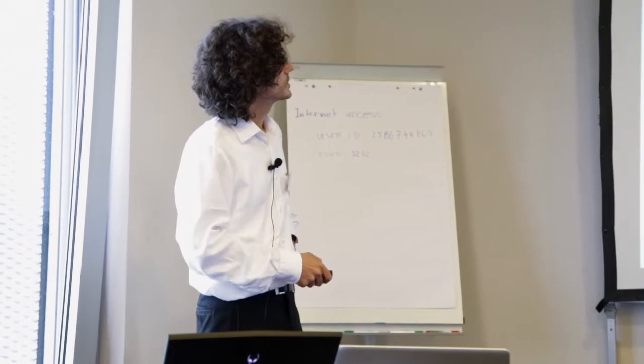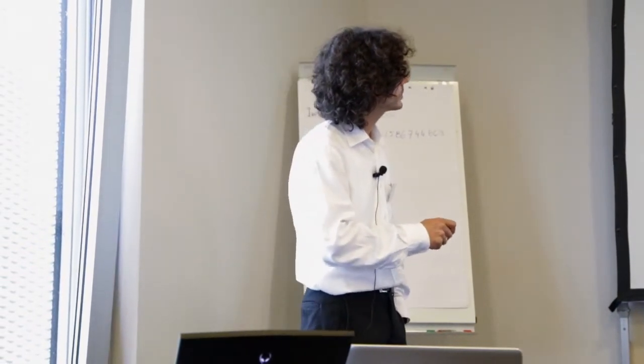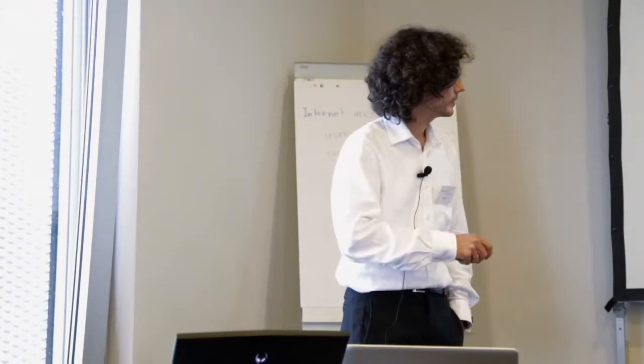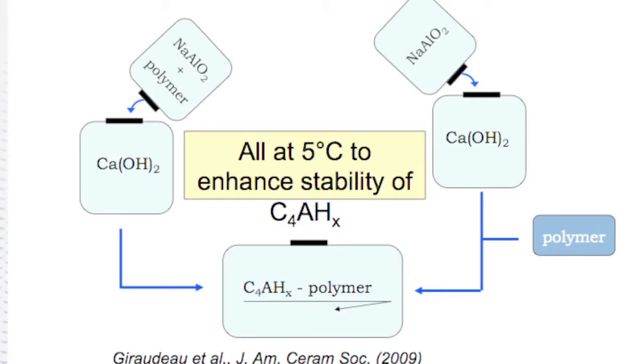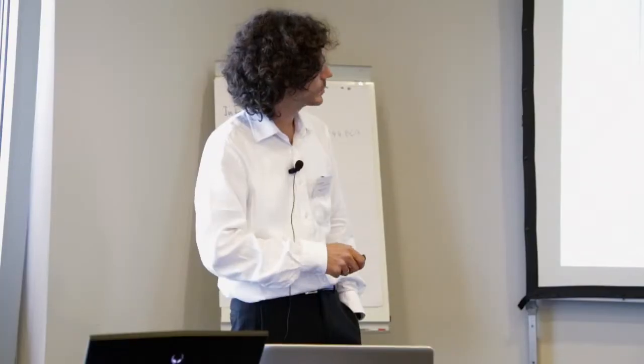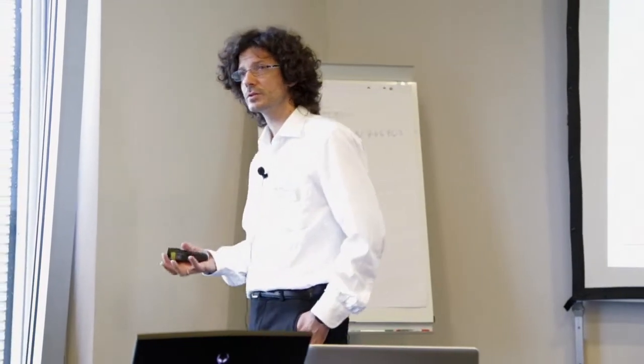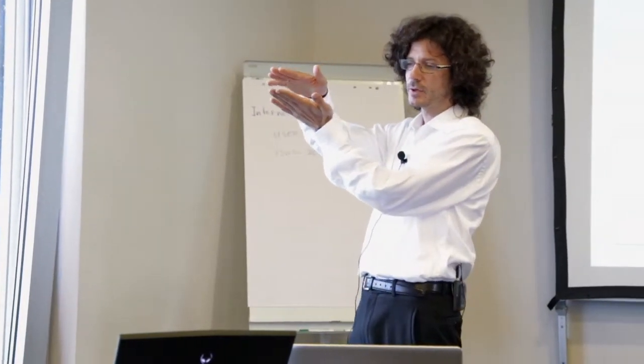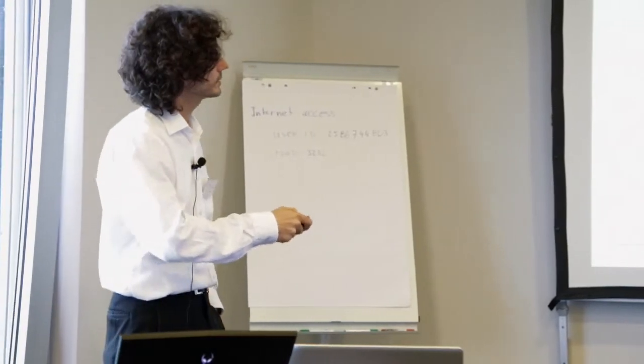Okay, so the approach taken in this core project was one of precipitation. That was the main approach. So solution of sodium aluminate with polymer mixed with a calcium hydroxide solution leading to the precipitation of composite C4AHX polymer phase, but also the possibility of precipitating this phase without the polymer and adding it subsequently. And by keeping everything at a low temperature, we avoid the conversion to the cubic phase. So we're testing whether these layers, once formed, make it possible for the polymer kind of to creep in and move the phases apart. So that was the real reason why working at 5 degrees here.